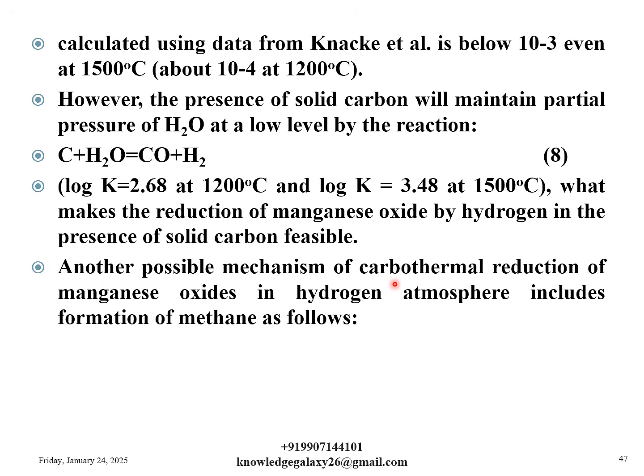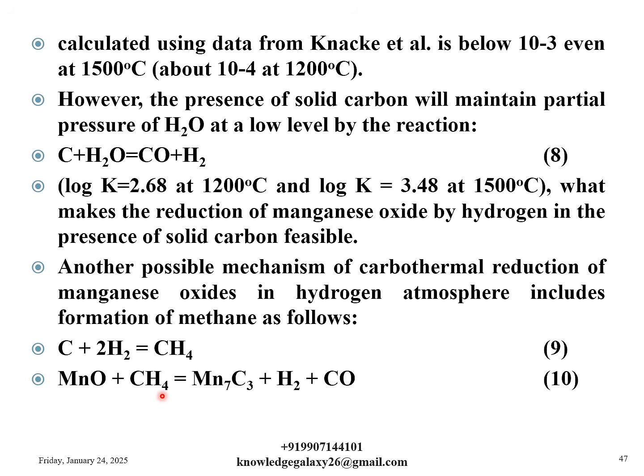Another possible mechanism of carbothermal reduction of manganese oxides in hydrogen atmosphere includes formation of methane as follows. C plus 2H2, this gives CH4. This is the equation number 9. MnO plus CH4, this gives Mn7C3 plus H2 plus CO. This is the equation number 10. My dear friends, please note and observe this equation very carefully, because this equation provides two reducing agents, that is hydrogen and carbon monoxide. So it is very important to note and to keep in mind.